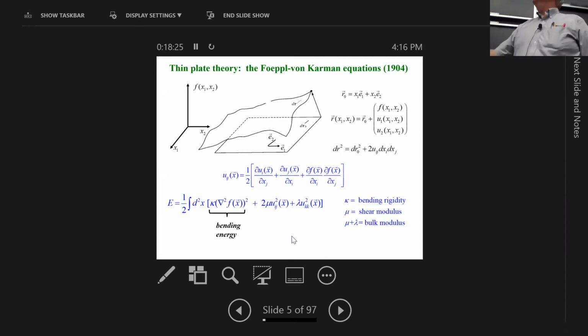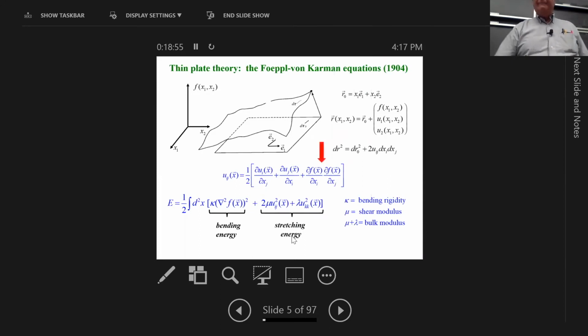So there's a bending energy shown here. There's a stretching energy that comes from the contractions of the strain tensor. This bending energy is very soft. It turns out rotational invariance means that the dependence has to be the Laplacian of F squared. This kappa is another elastic constant called the bending rigidity. And then in 2 dimensions, mu is the shear modulus and mu plus lambda is the bulk modulus. So that's the problem here. And now the effect of this nonlinearity is what's going to cause some of the remarkable things that I'll tell you. But let's just do something very simple at first.